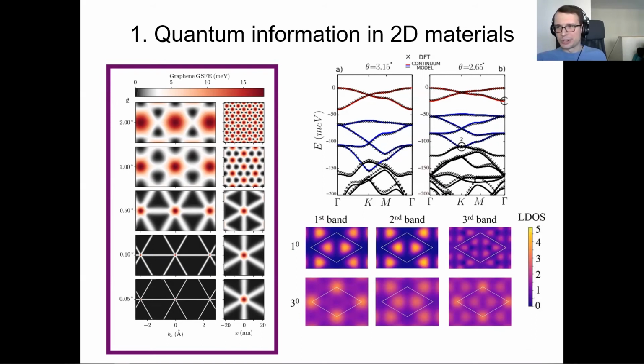So you'd have to study the phonon-electron coupling and the screening effects and the Coulomb effects and the tunneling to the substrate. But these 2D materials are usually fabricated with extremely high quality, so they have very low defects. And I think it's very likely that in maybe another 5–10 years, they're going to have much higher quality quantum dots than the gallium arsenide systems, which are prone to a lot of fabrication defects, which cause a lot of decoherence. So here, the quantum dots are not fabricated by pattern gates. They're fabricated by the interface between the materials, which is a self-cleaning substrate. That's why they're able to get such good transport quality in graphene.